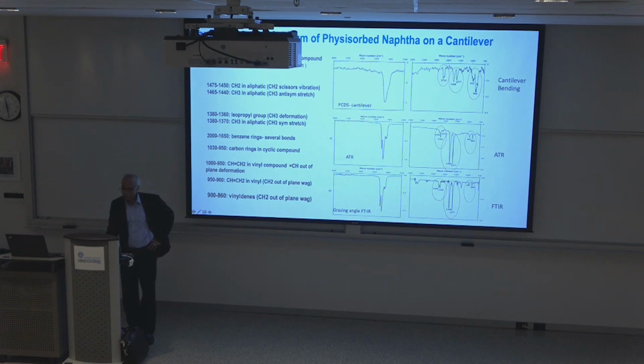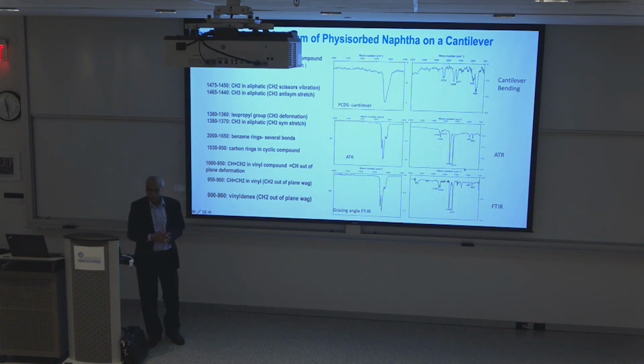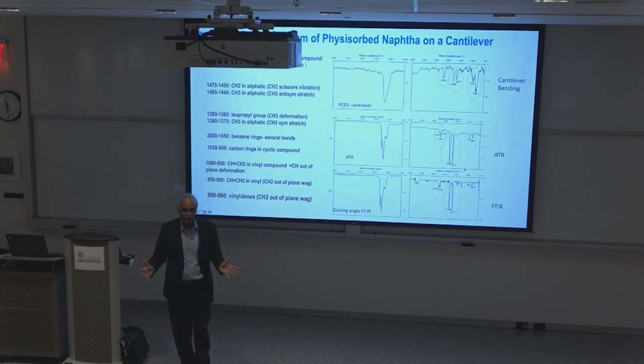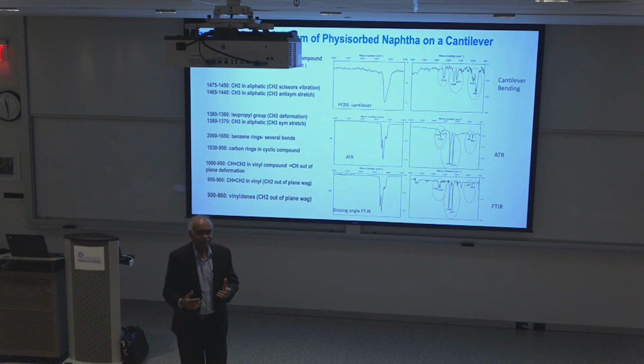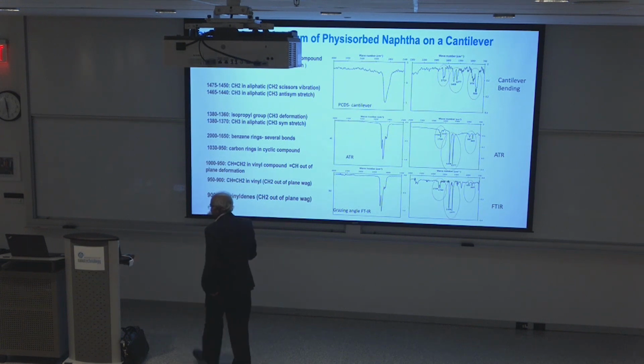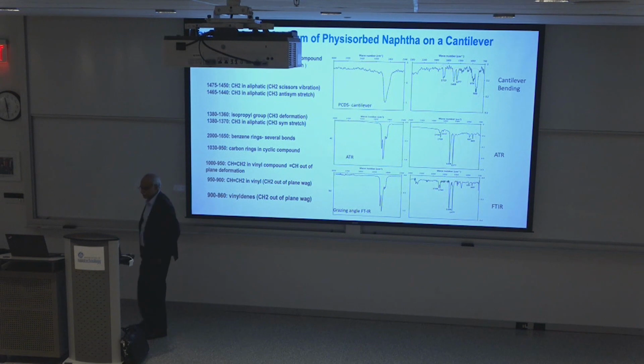And this is the ATR and the FTIR. You need a lot more material and a bulky setup. That's so important. So this cantilever can basically do the exact same thing, but with a picogram amount of material absorbed, from which we get the spectrum. And this is the naphtha. Naphtha is a complex molecule, but if you look at the spectral matching, you can identify all these peaks.